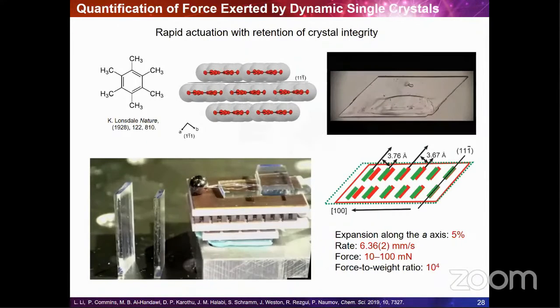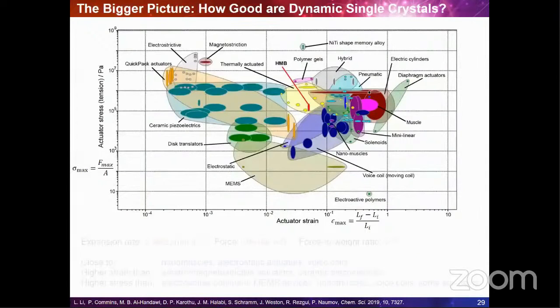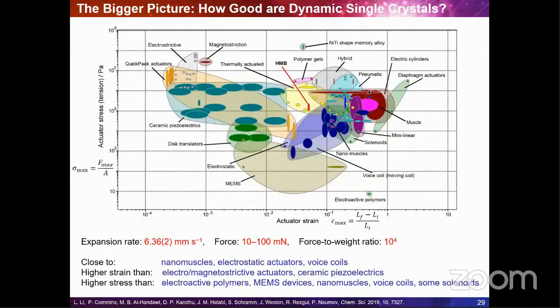So an actuator performance chart of this compound reveals that the performance of this material is close to that of the nanomuscles, electrostatic actuators, and voice coils, with a very high strain, higher than electro and magnetostrictive actuators, and even ceramic piezoelectrics, and stresses that are higher than that of the electroactive polymers, MEMS devices, nanomuscles, voice coils, and some other solenoids. Moreover, the crystals of these materials are mechanically compliant and can be bent reversibly and shaped to fit into the desired application, which is not always possible with other materials.